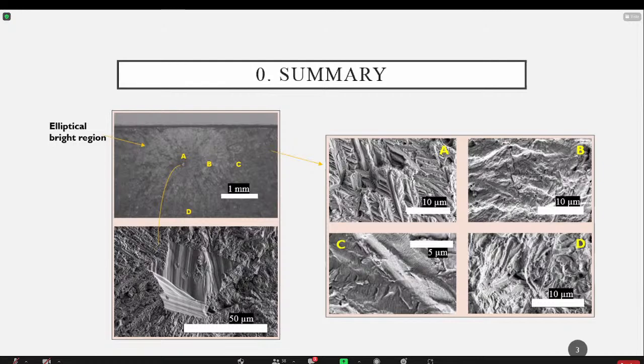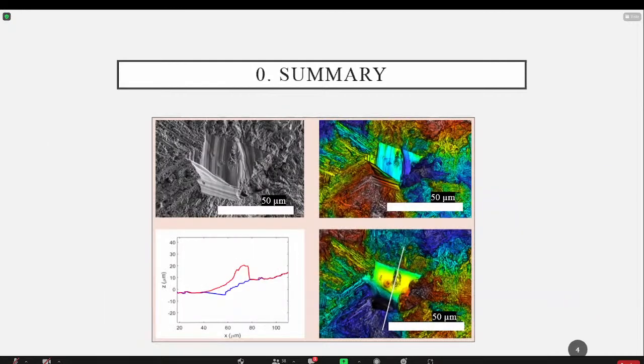We found this pattern in all these specimens that we analyzed. So it's interesting to go deeper into the defects. We analyzed with a scanning electron microscope and also with confocal microscopy both sides of every defect that we found. And we also extracted from the confocal microscopy image a vertical profile of the specimen, which you can see in the bottom left-hand side.